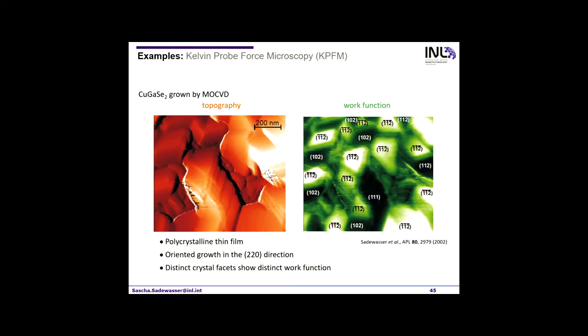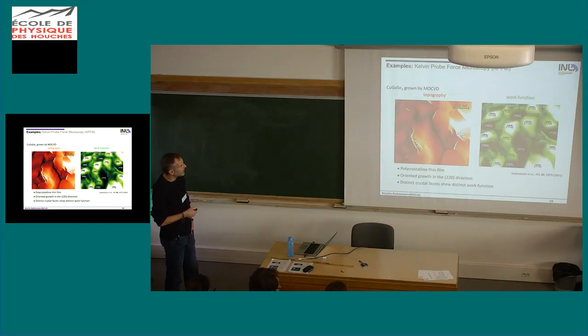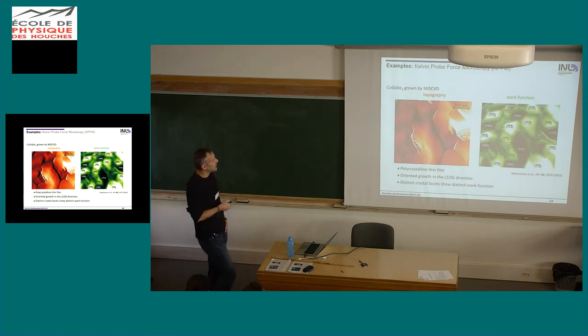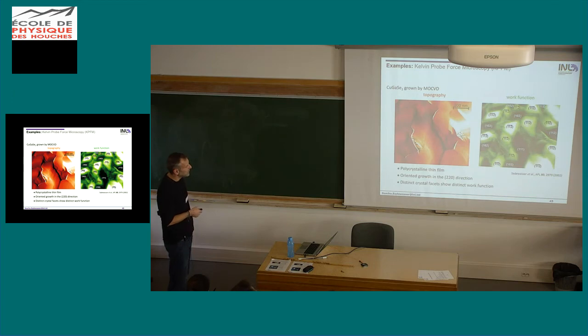And now a couple of examples. So initially, just what you can do is you can image a copper gallium diselenide. In this case, it was grown by MOCVD. So there was some textured growth here in the (2 2 0) direction.